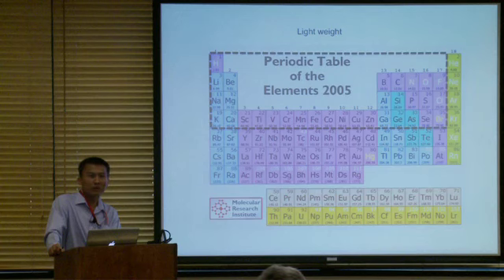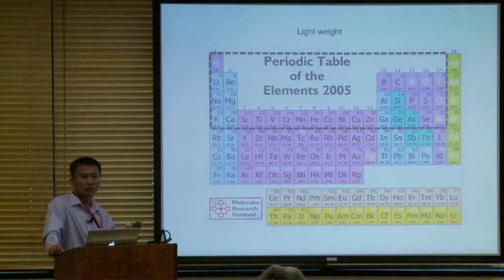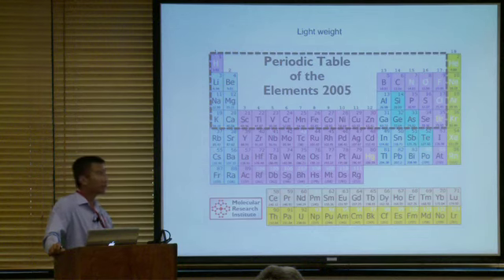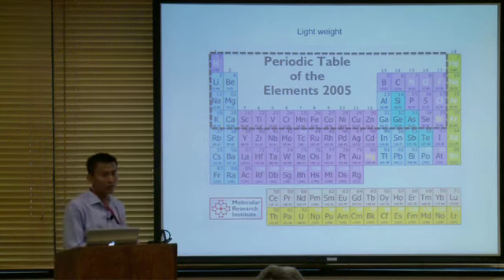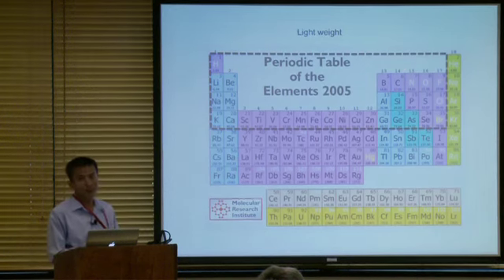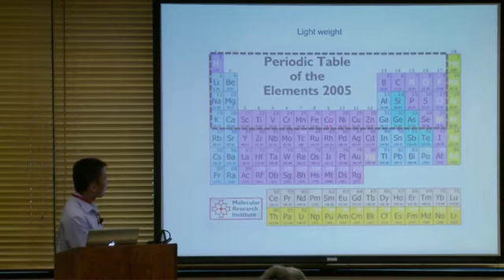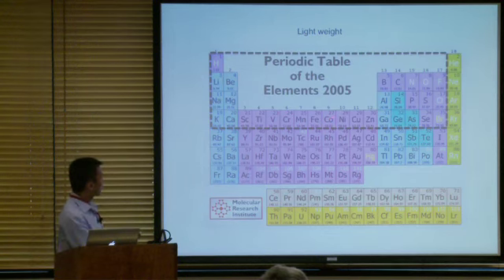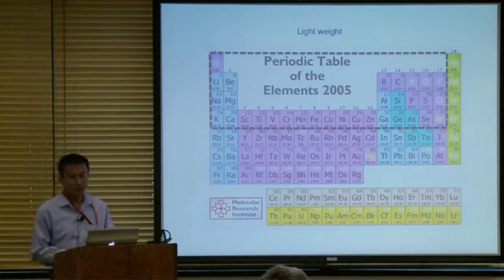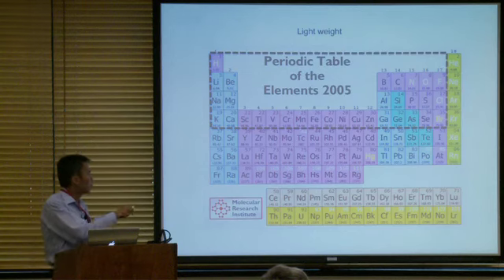You see certain battery technology phase out. One reason, not for all the reasons, just one possible reason among all, can be that it's not abundant, or it's too heavy. It's not within this box. Now you look at the lithium-ion battery: we use carbon, right? That's very lightweight. We use lithium cobalt oxide. Cobalt is right here. You would like to move to the front a little bit so you can reduce the weight a little bit. In the future, if you look for large-scale applications, it should be inside this box. Don't go beyond this box.